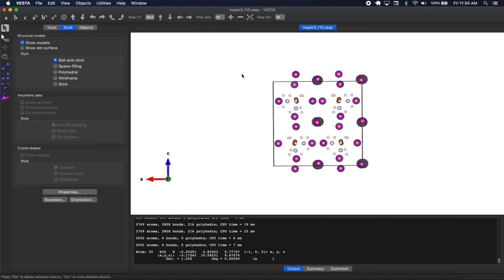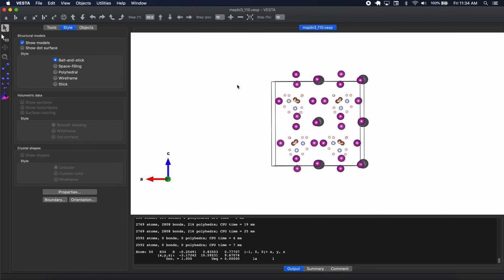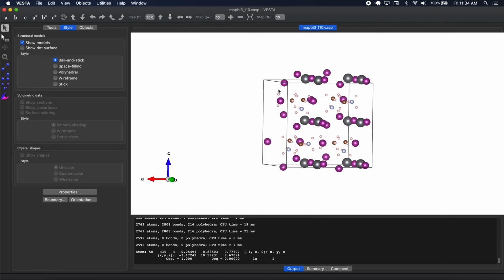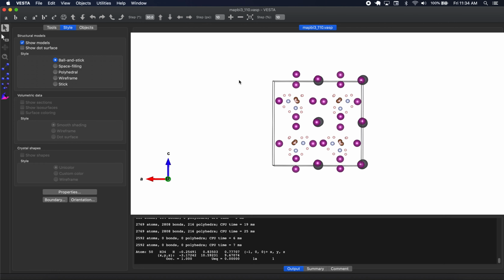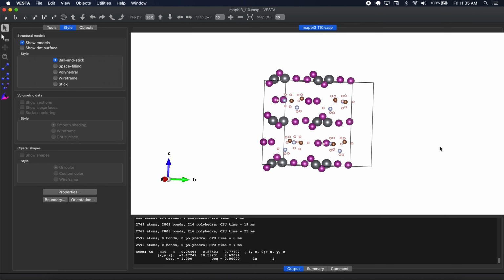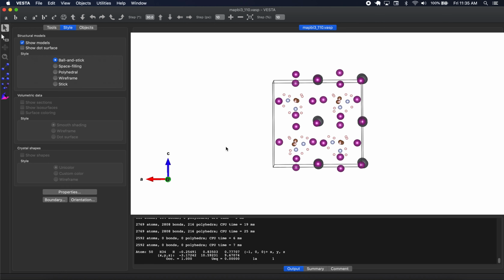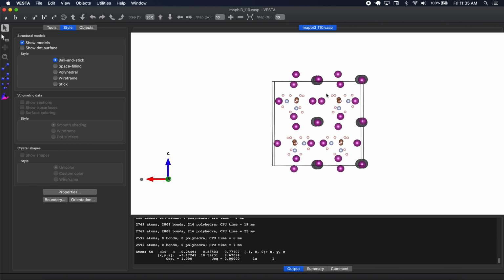Okay, so this is pretty bizarre, but trust me, this is what we need to keep here. Well, I mean, there's a chance I could be wrong, but basically you want to maintain this proper sort of termination in the dimension where you have the vacuum. Okay, and this is what a lot of codes that make slabs are struggling with. They would have just cut it here, okay? But you need this extra termination to maintain the charge neutrality.